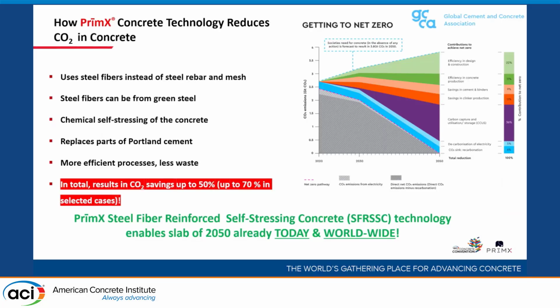To sum up, how do we achieve savings with this technology? First of all, we use steel fibers. I was looking at a lot of sessions today that explained, also in this session, why steel fibers, or fibers at all, are more beneficial compared to rebar in terms of embodied carbon savings. We can also make these steel fibers from green steel. A typical number for steel fibers, as I think was mentioned in this session, is, for example, 1.2 tons of CO2 per metric ton of steel fibers, and we can apply fibers that cut it down to 0.3 tons per ton of steel fibers.